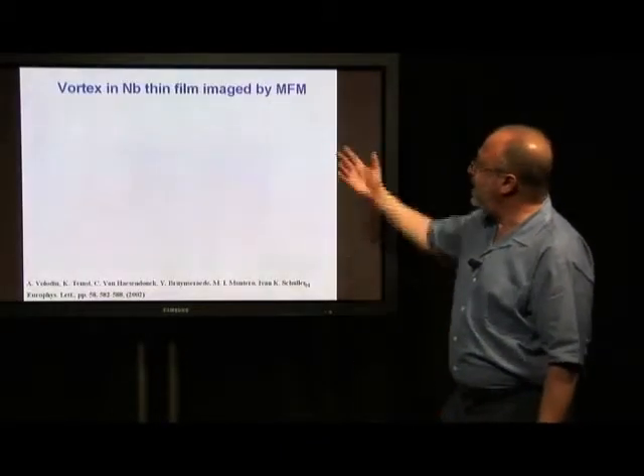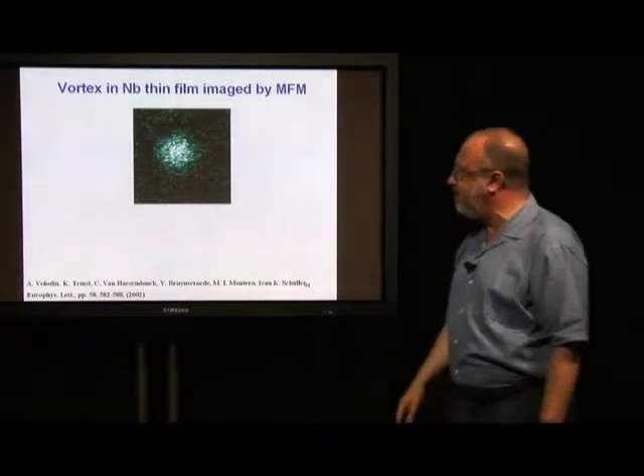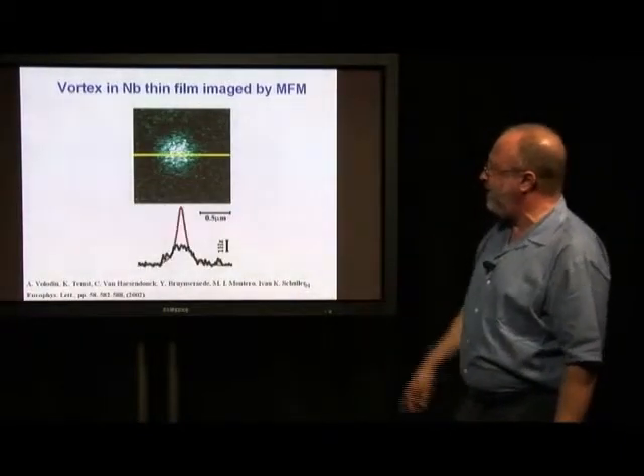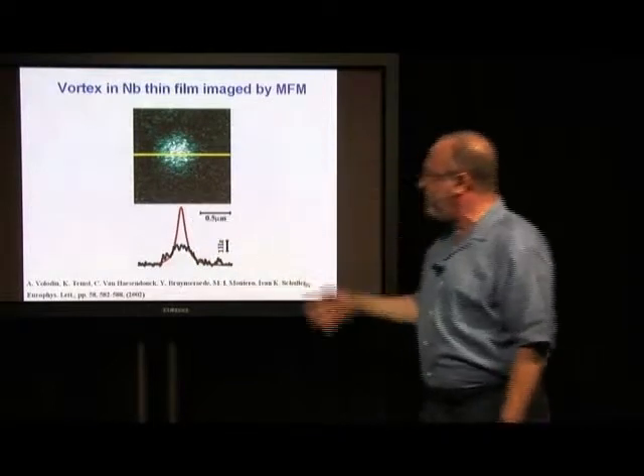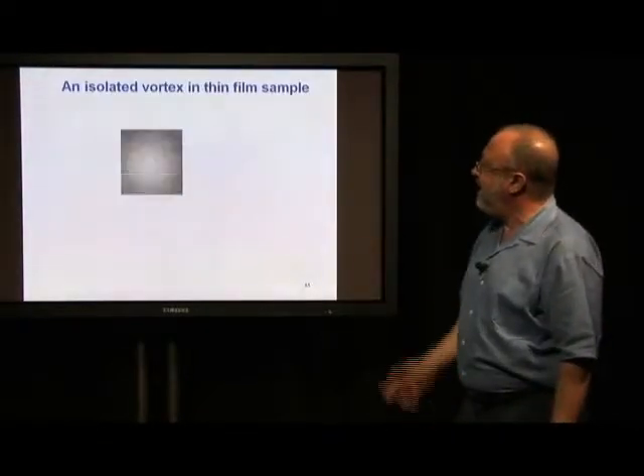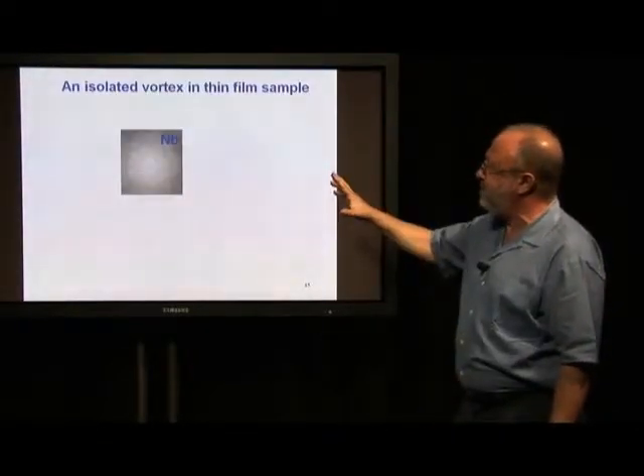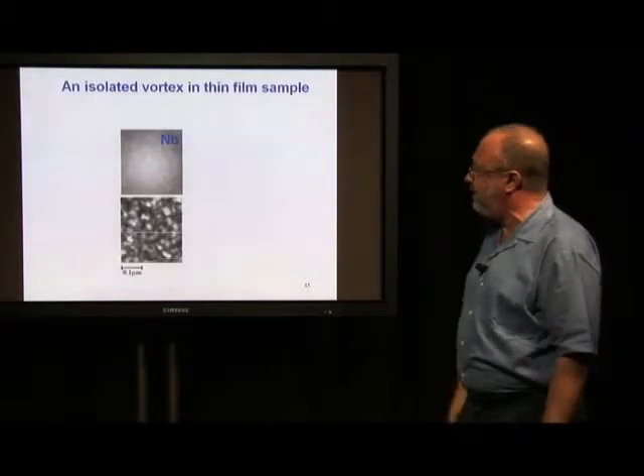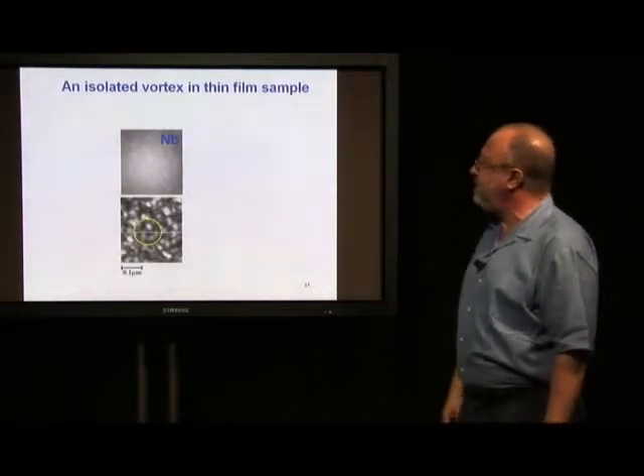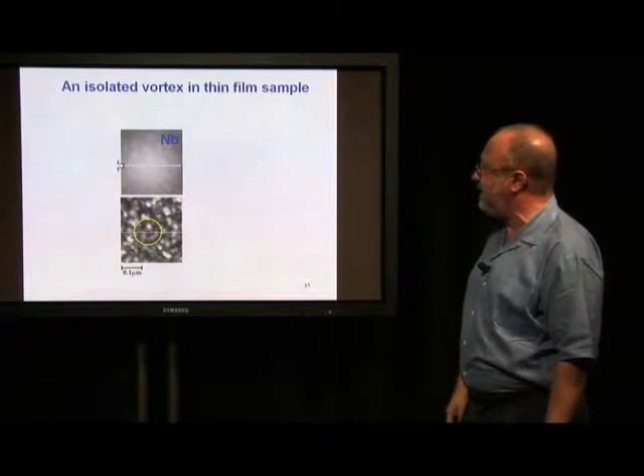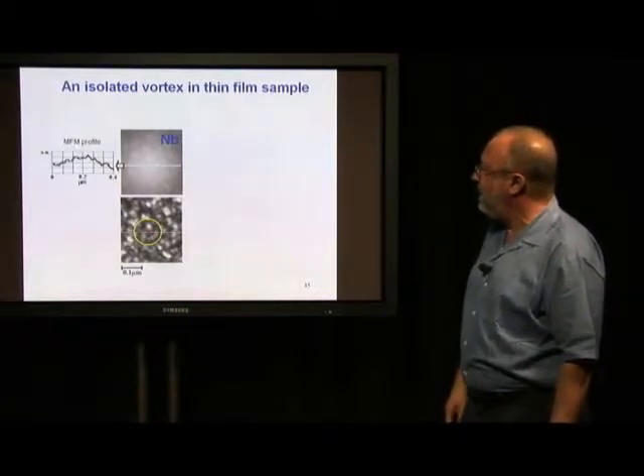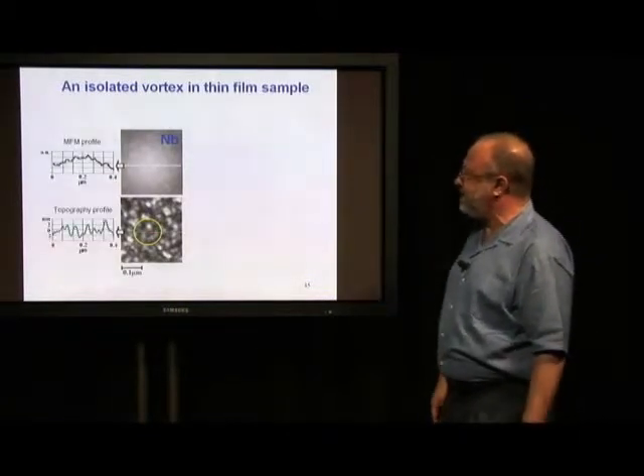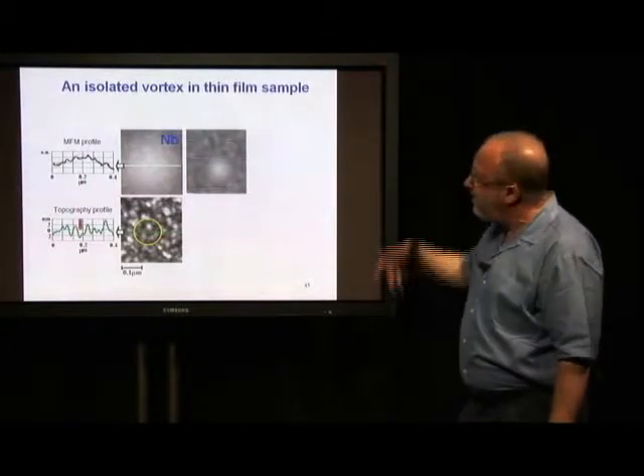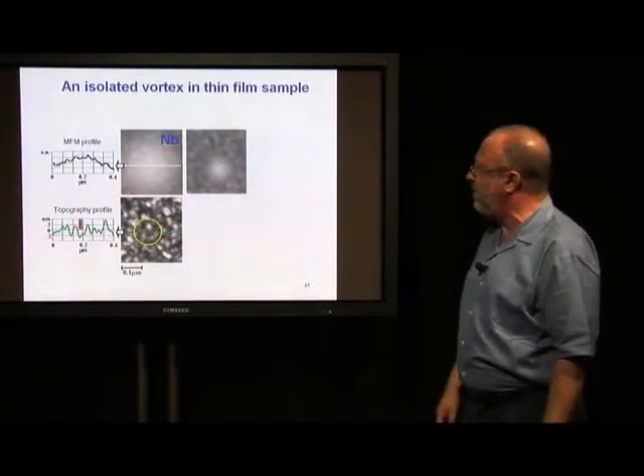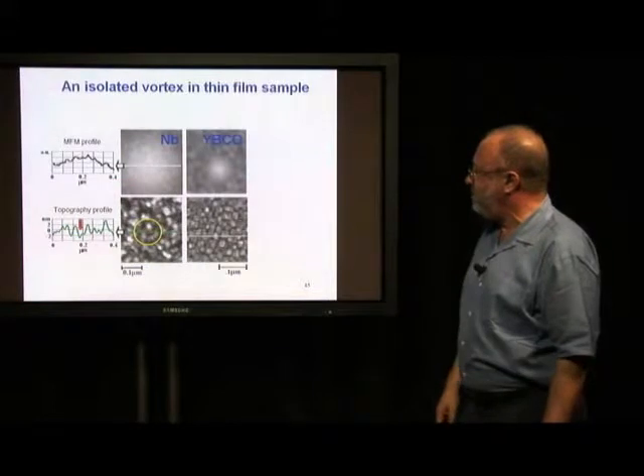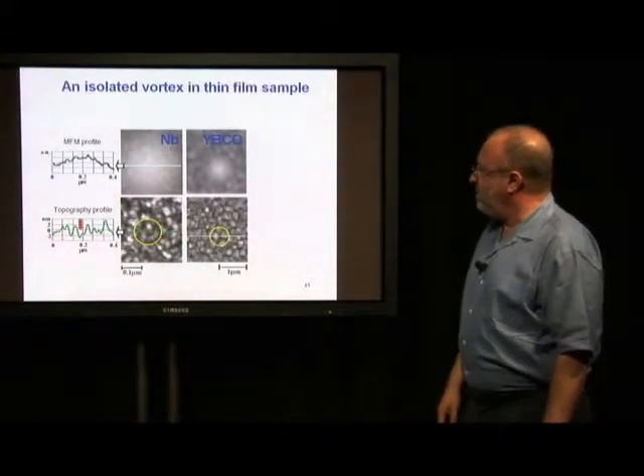Now, in a niobium film, we have imaged this also, and we have looked at the magnetic field profile and all kinds of detailed things. This is for isolated vortices for the moment, what I'm showing you, and we did this both for niobium and for high-temperature superconductors like YBCO, and I'll show you an example of that in just a second. So we have studied where these vortices locate compared to the topography of the sample, and so on. And so these are the results.